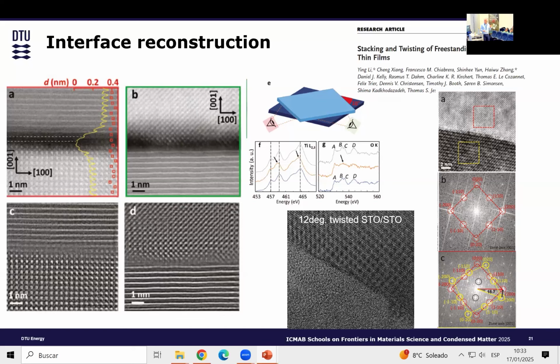We are doing some work on it. I think the contrast comes from dislocations. We think that there is a dislocation network when you twist the material. So it's not just the moiré; there are also dislocations because the materials try to fit each other and cause dislocations at the interface. We also did analysis and could see some oxygen vacancies in there. We can also see the moiré structure. So we observe things that people regularly observe in 2D materials when you put two materials together. Now the question is, what happens at the interface?